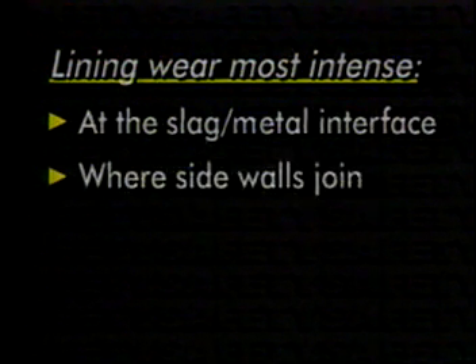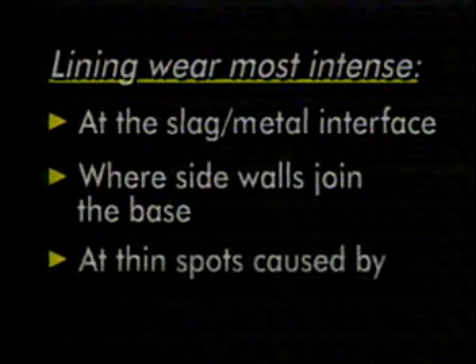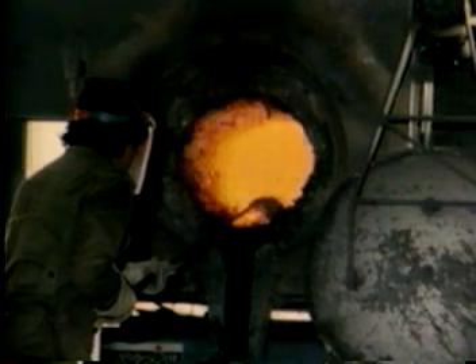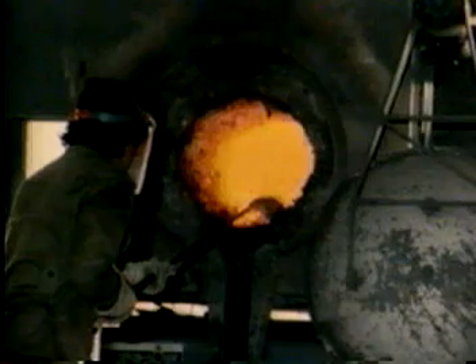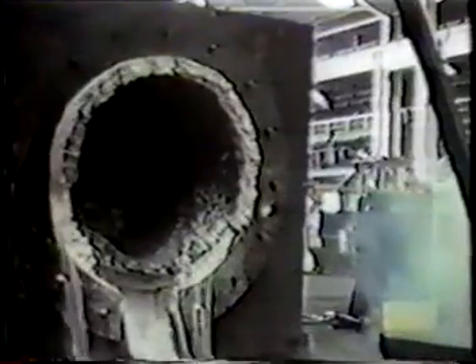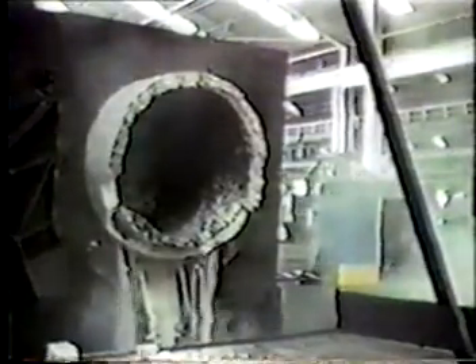In induction furnaces, refractory linings and crucibles are subject to normal erosion due largely to the inductive stirring caused by the induction furnace's magnetic field. In theory, refractory wear should be uniform, but in practice the most intense wear occurs at the slag metal interface, where sidewalls join the base, and at thin spots caused by poor lining procedures. The entire furnace should be visually inspected whenever it is emptied. Special attention should be paid to these high wear areas, and observations should be accurately logged. Eroded or damaged linings must be repaired or replaced immediately.